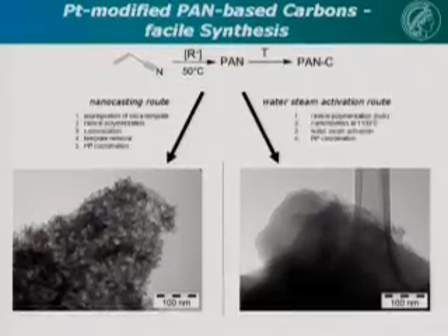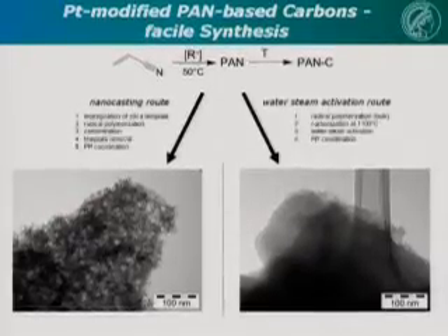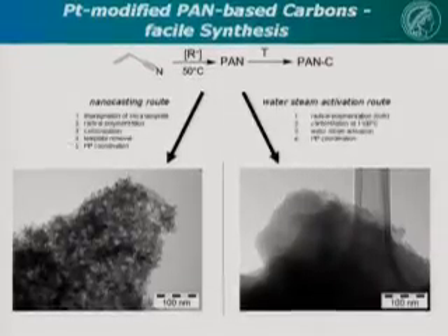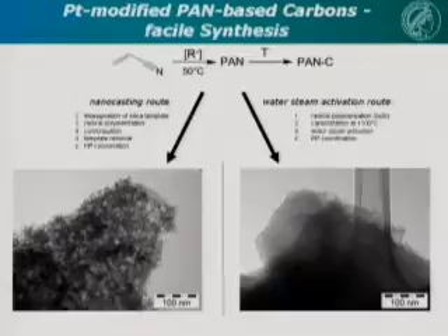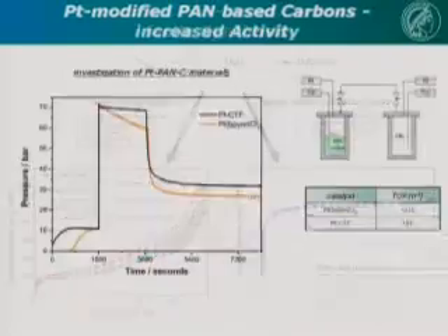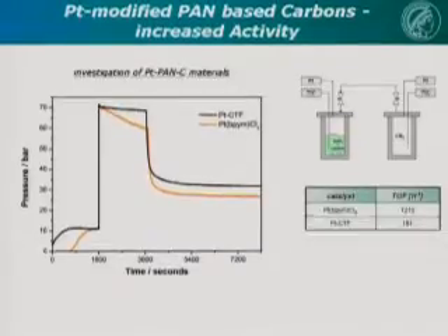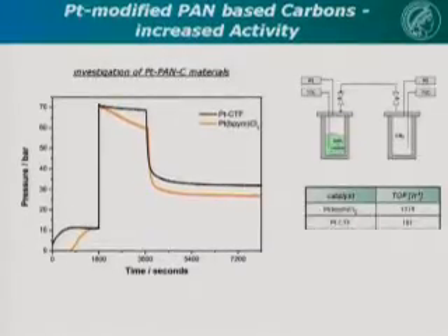And then we went further, looked at other polymers, at least 20 different nitrogen-containing polymers. We were successful with polyacrylonitrile-based ones. So we synthesized polyacrylonitrile, carbonized, and you get a nitrogen-containing, highly porous carbon, either microporous, depending on how you activate, or mesoporous, if you do it by a nanocasting. Don't want to discuss this. But then did again the catalytic evaluation.